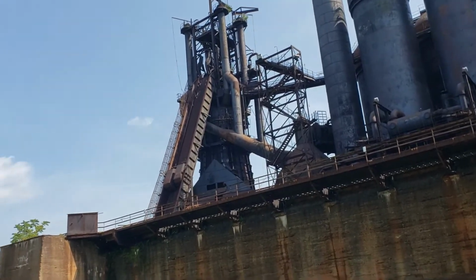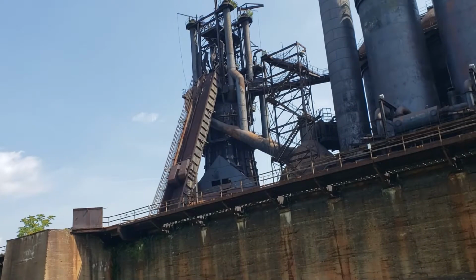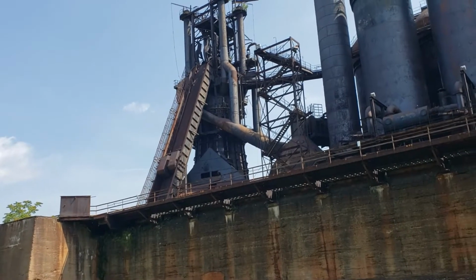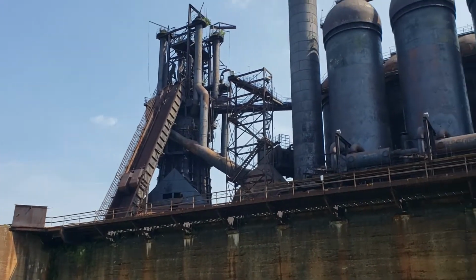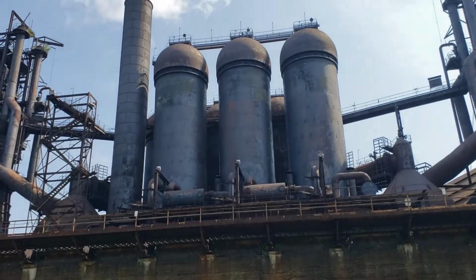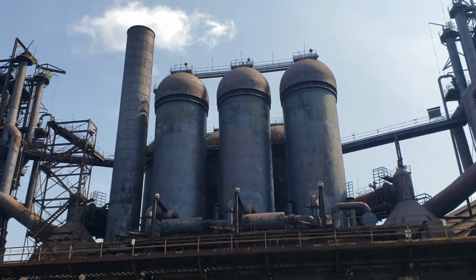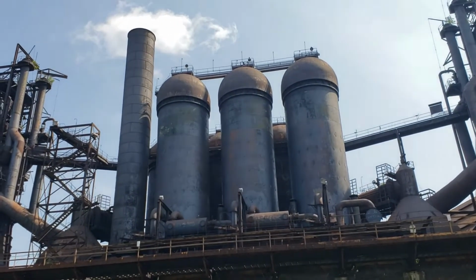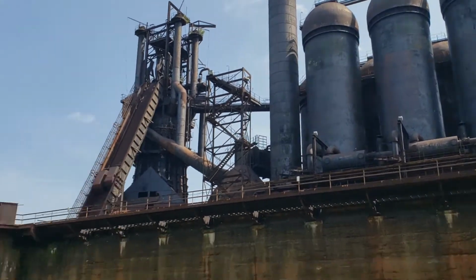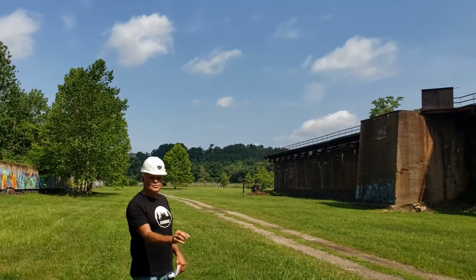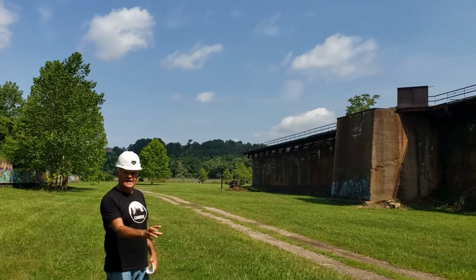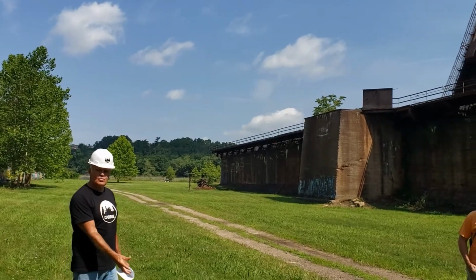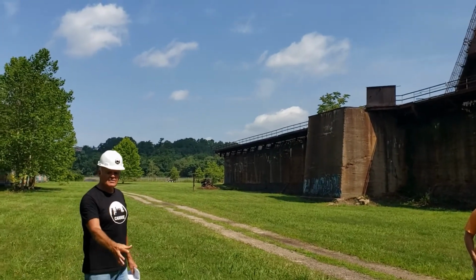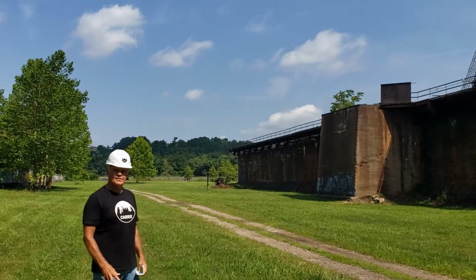Bill, what kind of temperatures were these operating at? The stoves would heat the air to 1800 degrees. Okay. The furnace would fire the blast air in the bottom, and at the tip of those nozzles, which were called tuyeres, the temperature would be 4,000. That would be the highest. When the iron came out, it was 2,800 to 3,000 degrees.